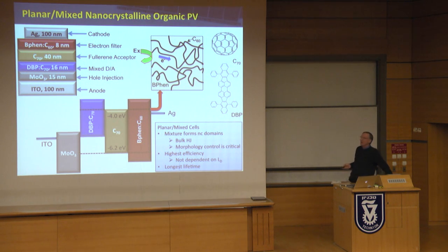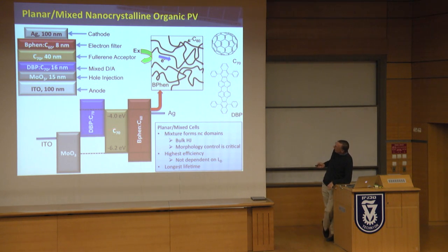So we're using C70, which is broadly absorbing across the visible, as the acceptor. And you can see its energy levels extend across, because we also have a blocking layer. And the blocking layer is very important because if an exciton is generated here, it can easily drift over to the silver and quench. And also you want the optical field to be maximum in this active region. And of course, we know that the optical field has a node at the silver contact. So therefore, the maximum has to be placed somewhere in here. So this has to be a transparent, wide energy gap region.